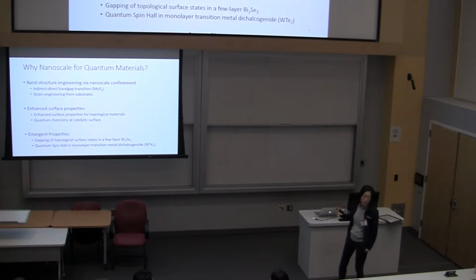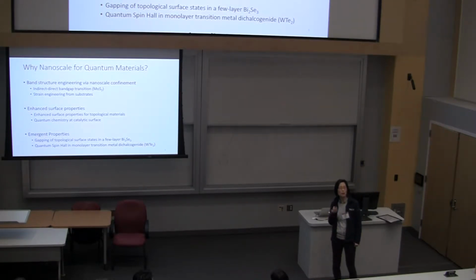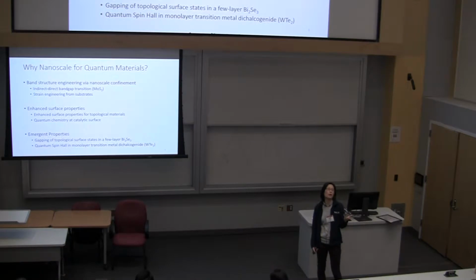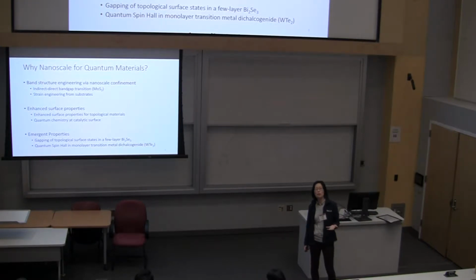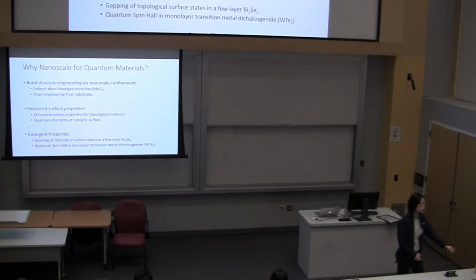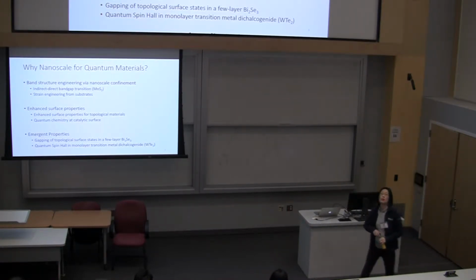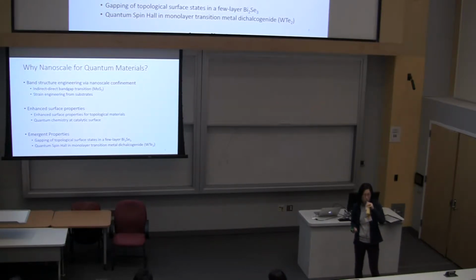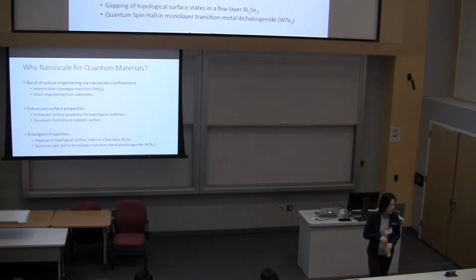Emergent properties. Some examples of emergent properties at the nanoscale in the context of topological insulators. As you make the topological insulators thinner and thinner, the top topological surface starts to couple to the bottom topological surface, and you'll then gap the surface state. For bismuth selenide, that transition happens around 5 quintuple layers thick. Tungsten ditelluride is a semi-metallic Td phase layered material. As you get down to a single layer, there's a little bit of structural distortion, and you get a quantum spin Hall state, right? So that's a topological state that comes around in the single layer limit.